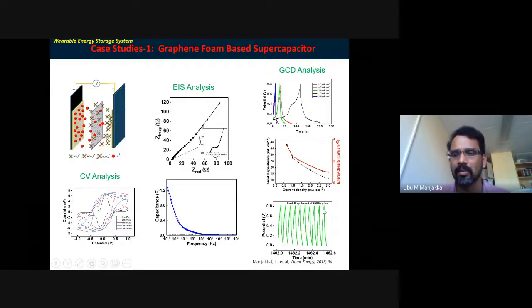A normal battery will work maximum 3,000 cycles, depending on the material, because it may react in the electrochemical reaction. But in my device, I got 25,000 cycles of operation, and this is the last 10 cycles of 25,000. So you can see that it's still fully working after 25,000 cycles.